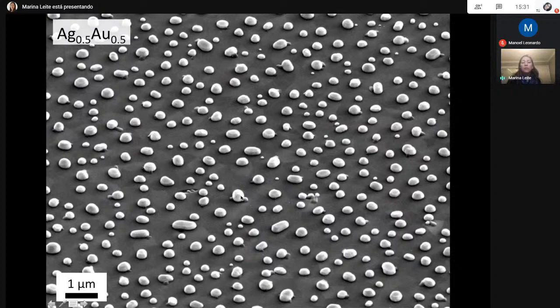But what I like about this method is that, one, after doing a lot of statistics, we do get a fairly narrow spatial distribution of the particles. Two, they were far away from each other in this case, so that we would not have a coupling effect between one particle and the other. So it was good for us to see how much we can control the near-field optical behavior. Third of all, it's very easy to scale up.